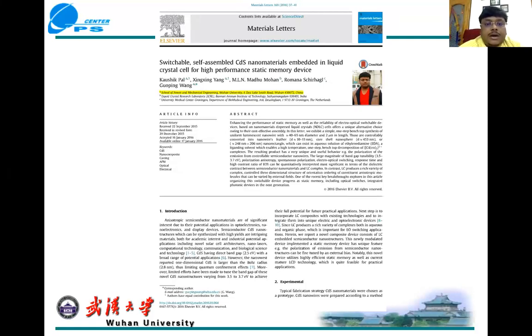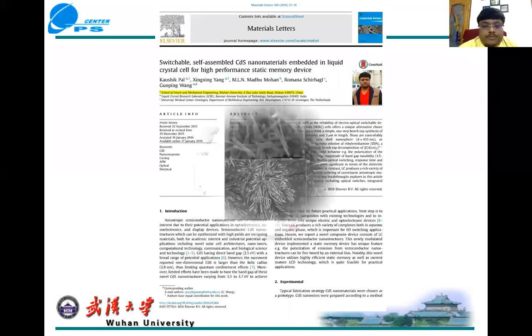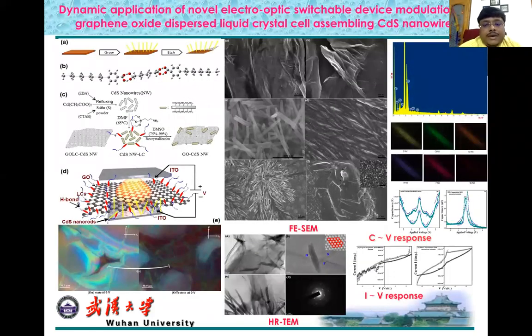It is a switchable and self-assembled CdS nanowire embedded liquid crystal cell for high performance static memory, or you can also use it as a static memory. Another work: you can see the first one is a graphene structure, and then we uniformly dispersed CdS nanowires. Then all those combined materials we placed into the homogeneous dispersion in liquid crystals. You can see a nano forest-like structure evolve, a nano tree, let's say.